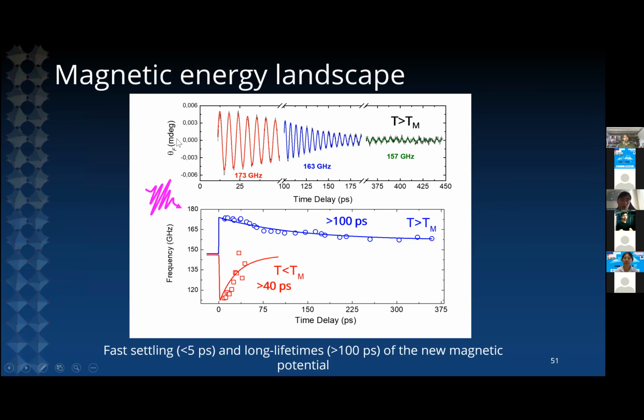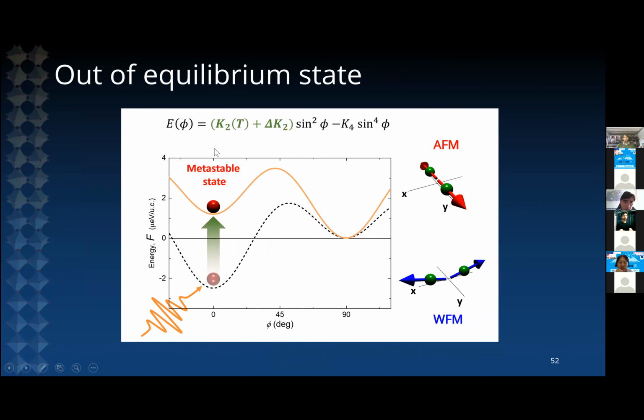So these changes occur very fast. In a few picoseconds, you have renormalized your magnetic potential, and then this relaxes back to the equilibrium phase on a time scale of the order of 100 picoseconds. And so we have direct access to an out of equilibrium state in which we have generated a metastable magnetic state with a softer potential through a change of the magnetic anisotropy K2 constant of the material.